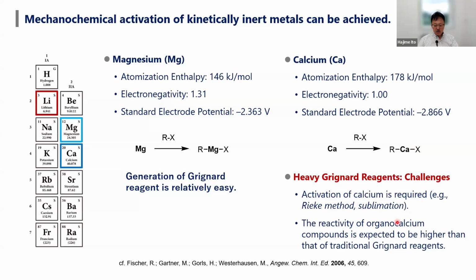In the literature, activation of calcium is required, such as the Rieke method or sublimation, or you can synthesize it through transmetallation of, for example, alkyl lithium and calcium salts. However, if you make organocalcium reagents, because the electronegativity of calcium is much lower than magnesium, you can achieve very high reactivity.